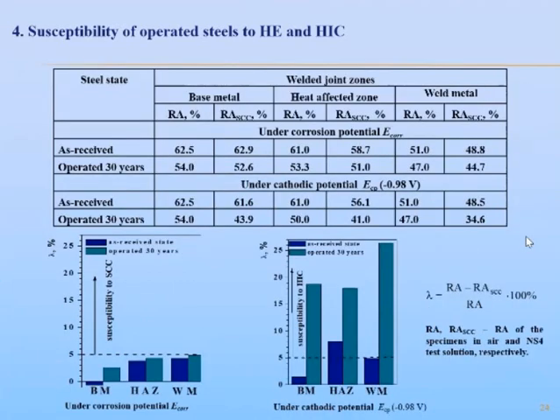And here is presented data on investigation of different zones of a weld joint of pipeline steel in as-received state and after about 30 years of operation. The specimens were tested by tension in an NS4 test solution simulating a soil environment and potential of cathodic protection. As can be seen from these results, the operated weld joint is characterized by higher sensitivity to hydrogen-induced cracking. Especially the weld metal of the operated weld joint is the most sensitive to hydrogen-induced cracking amongst the different zones of the operated weld joint.